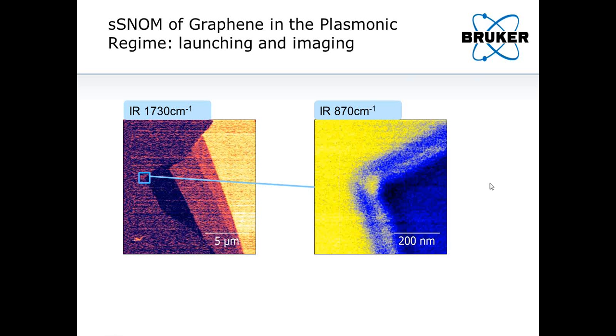So what's happening in this image to create this pattern is that the tip is launching a plasmon wave. It reflects off of the interface, comes back to the tip, and either constructively or destructively interferes with the tip dipole. And then that affects your scattered light that you detect in far field.